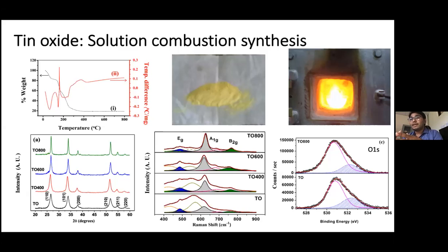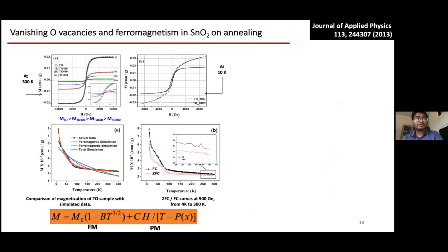So when I say oxygen 1s, the s basically says that it will not have any spin orbit coupling, and I shouldn't expect any splitting in the peak. But I was getting a high peak at higher binding energy, which essentially reflects that there is some fraction of oxygen which is near a non-regular crystallite location. So this was further confirmed.